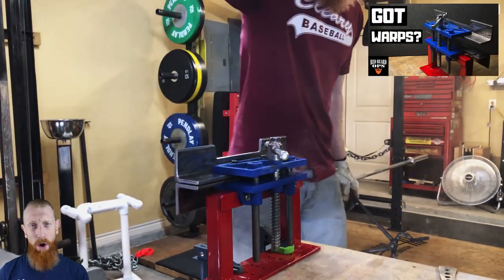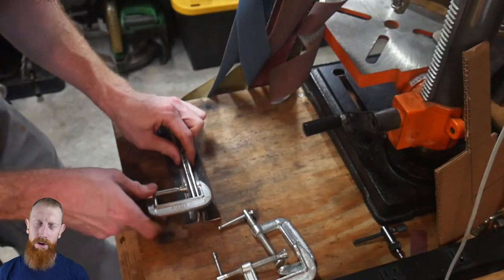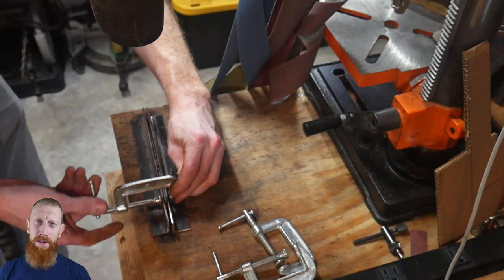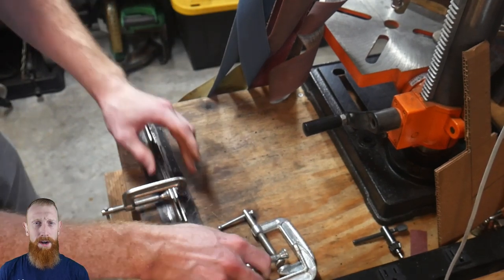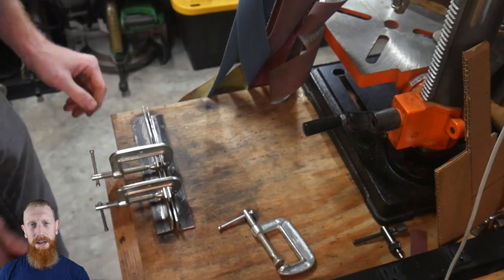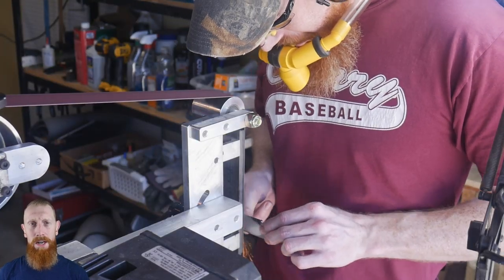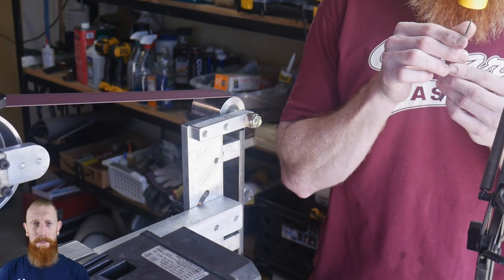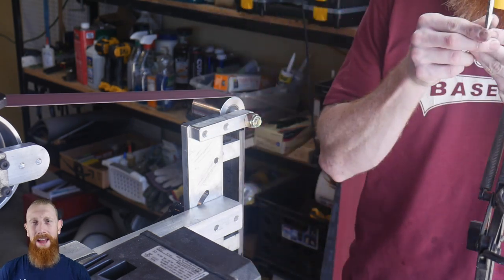This is one reason why I recently built a set of quench plates, so that I can hold the blade straight after my quench. I also clamp the blade between two pieces of angle iron during the tempering process so as to keep the blade straight during tempering and not allow the blade to move at all or shift during the tempering process.